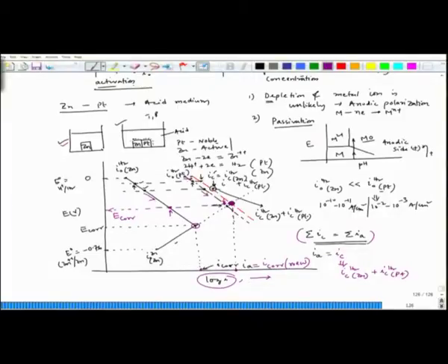Now, you could see that in this case 1, when we have connection of an active component with a noble component, the corrosion rate of the active component goes up enormously. This is the explanation of why it goes up, with the help of the Evans diagram.